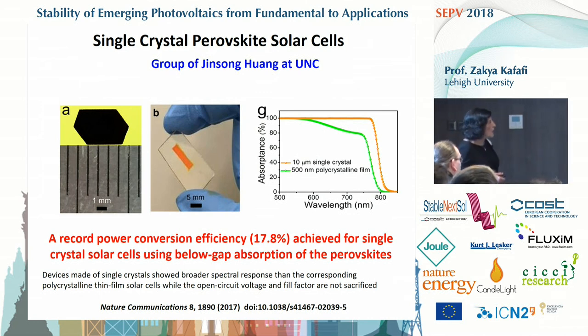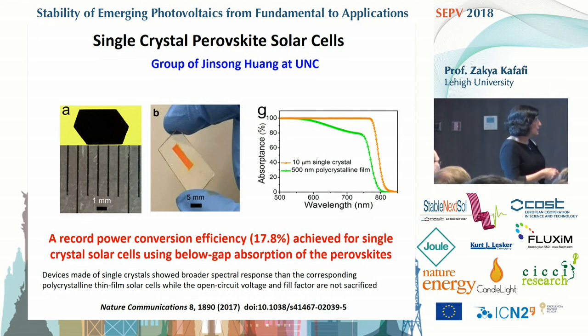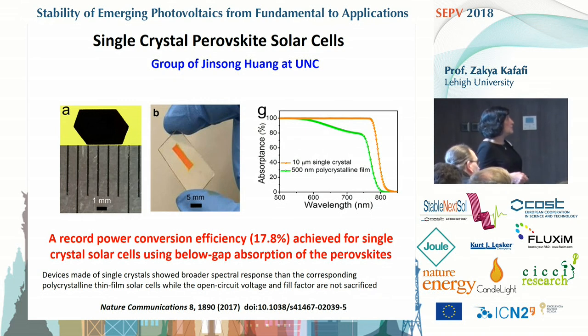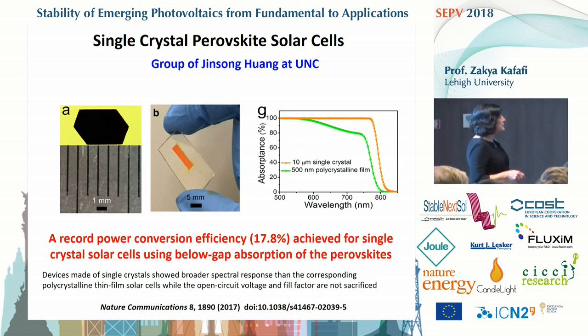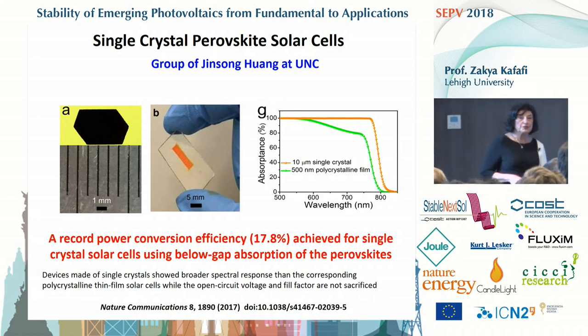The group of Jinsong Huang, who moved recently from Nebraska to the University of North Carolina, demonstrated a record power conversion efficiency that he achieved for a single crystal solar cell using below-band-gap absorption of the perovskite. If you look here at the absorption of the polycrystalline perovskite film versus a single crystal, you see that it has a much broader spectral response than the polycrystalline material, while the open circuit voltage and fill factor were not sacrificed.